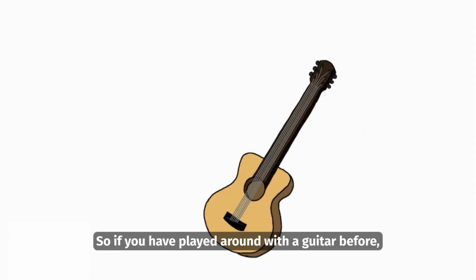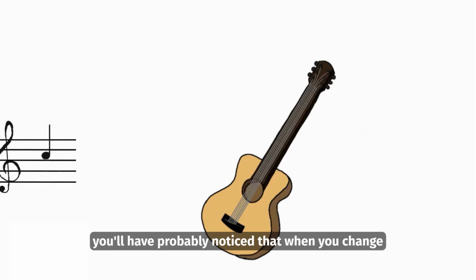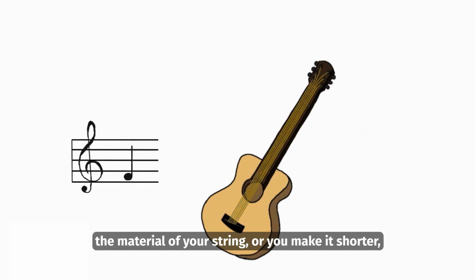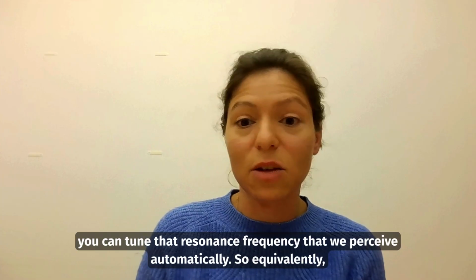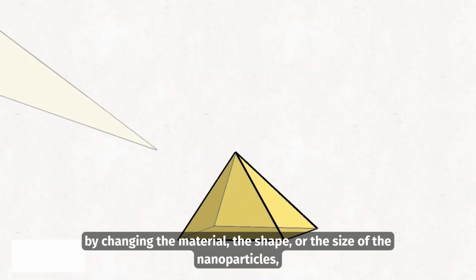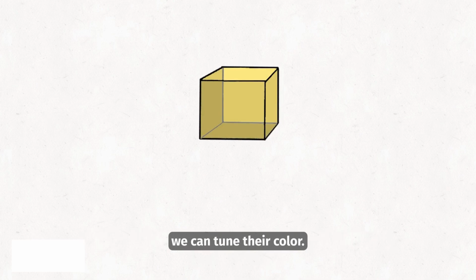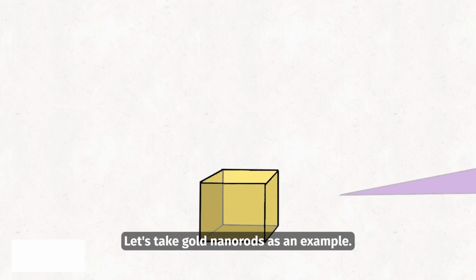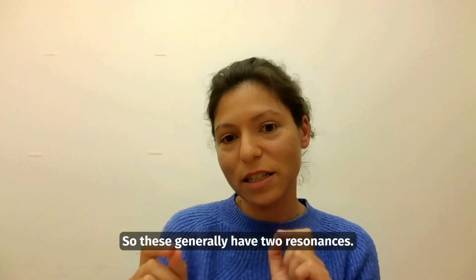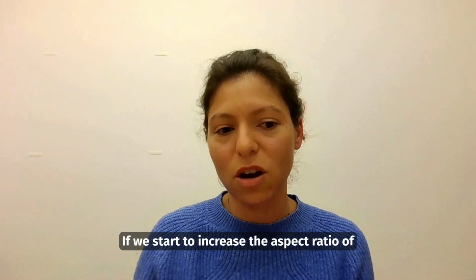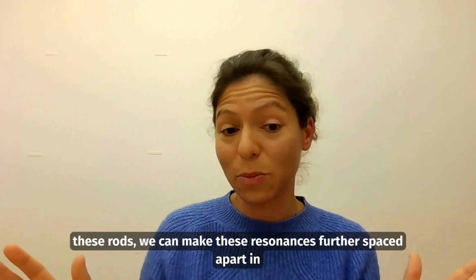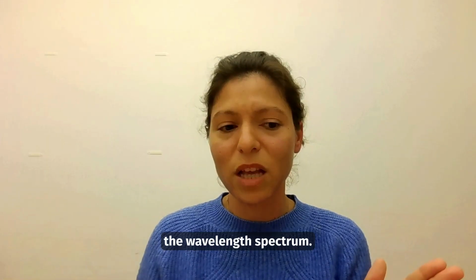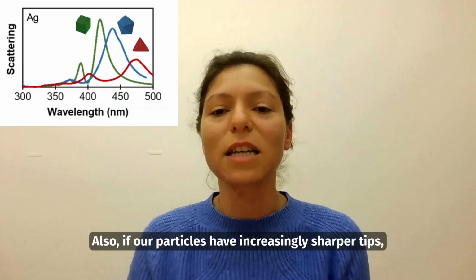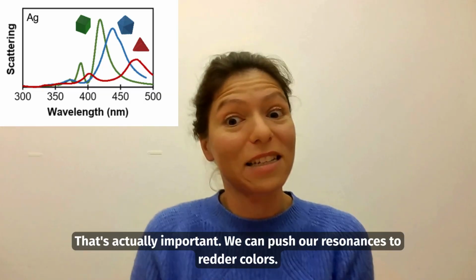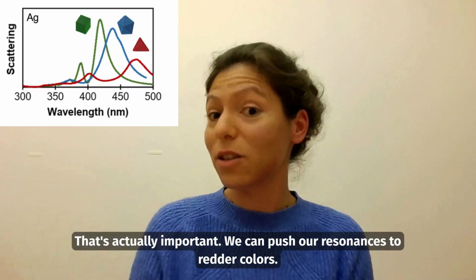So if you have played around with a guitar before, you'll have probably noticed that when you change the material of your string, or you make it shorter, or if you pluck a string that is thicker, then you can tune that resonance frequency that we perceive as the pitch. So equivalently, by changing the material, the shape, or the size of the nanoparticles, we can tune their color. Let's take gold nanorods as an example. These generally have two resonances. If we start to increase the aspect ratio of these rods, we can make these resonances further spaced apart in the wavelength spectrum. Also, if our particles have increasingly sharper tips, and this is really a fine detail that's actually important, we can push our resonances to redder colors.